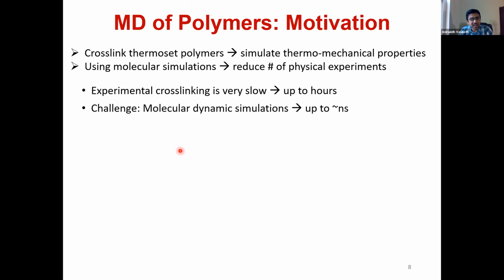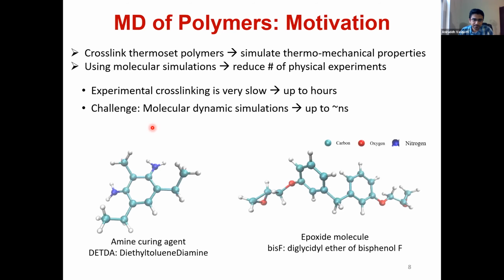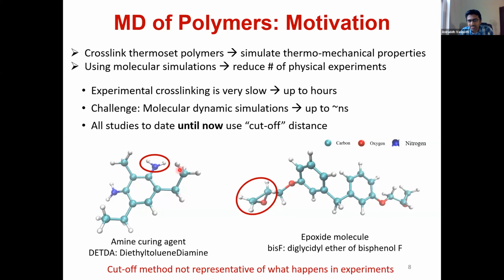Another challenge is that experimental cross-linking is very slow. If you try to cure an epoxy, it takes a couple of hours. Sometimes it can take a couple of days as well. But in molecular dynamics, you can simulate only a couple of nanoseconds. And the way around that people have figured out is that they'll look at the curing agent, and they'll look at the epoxide. They'll say, once the reactive sites are within a certain distance from each other, they cross-link. They just react. They call it the cutoff method.